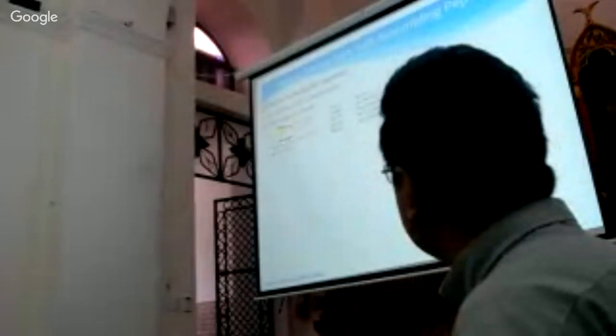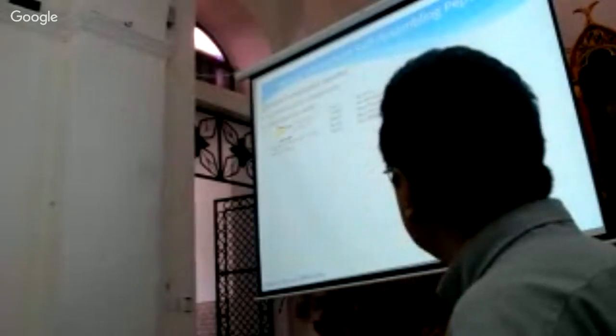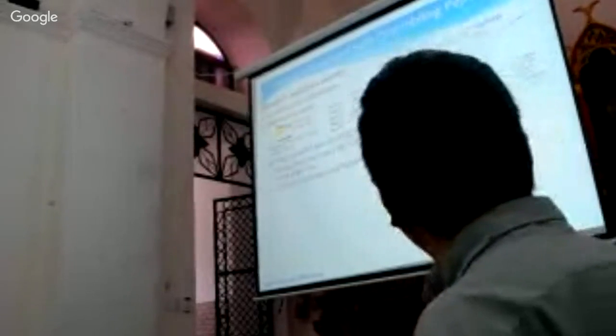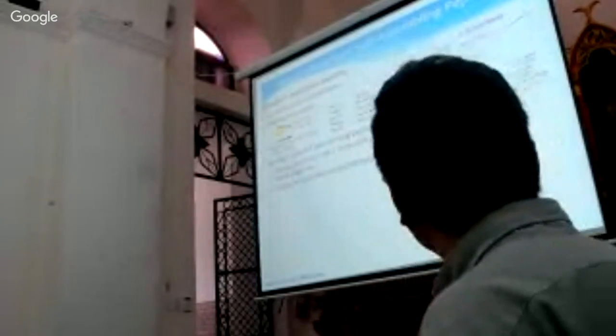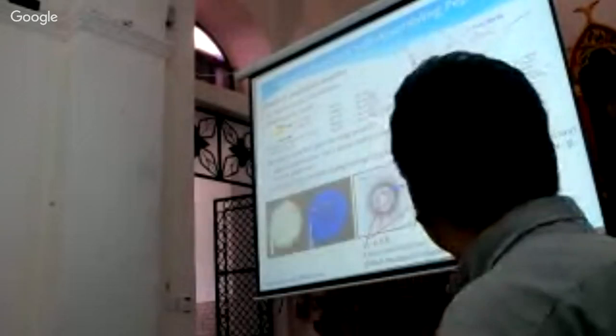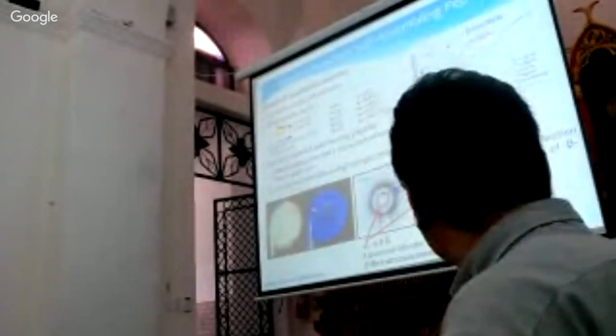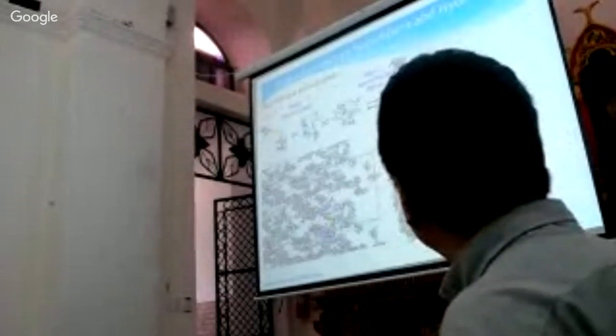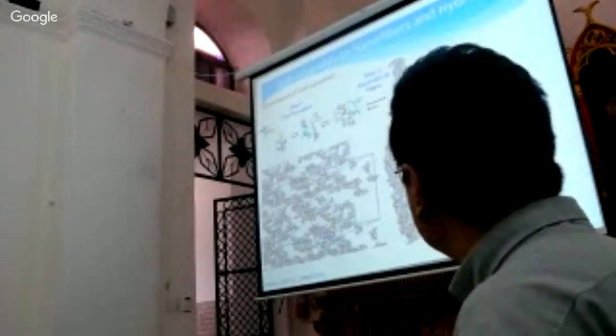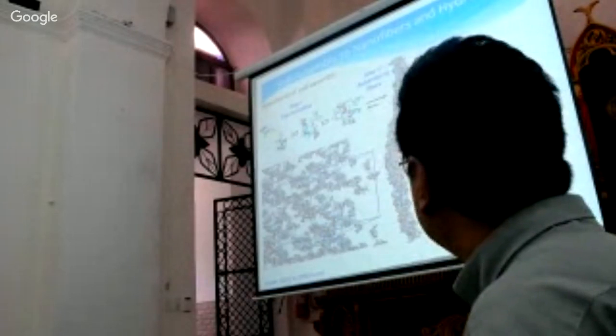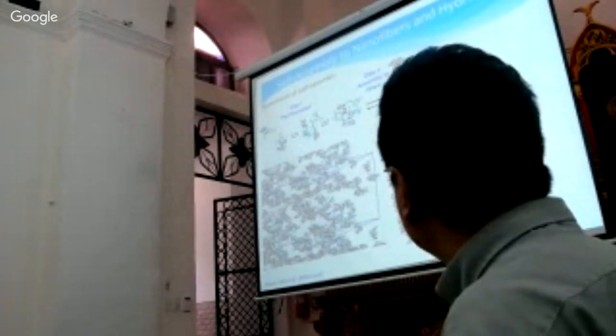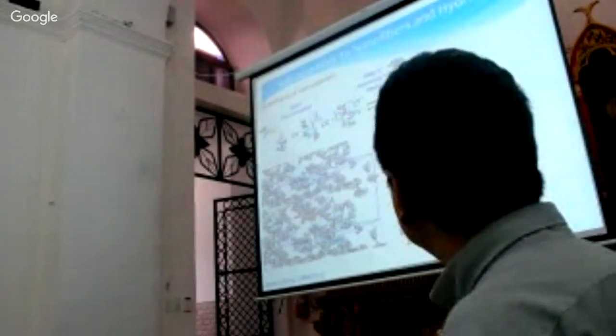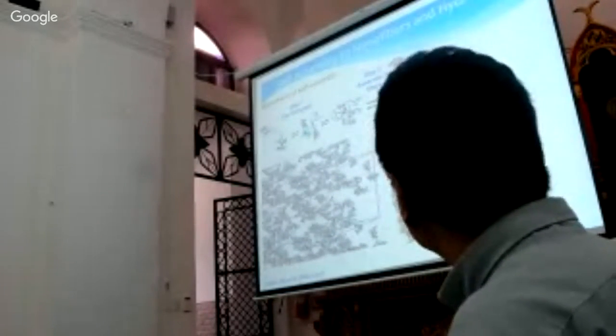The design rationale is to decrease the hydrophobicity from this end to this end, and then it will form a nice hydrogel that I'll show later. This is the secondary structure determined by the CD spectrum, and it forms beta-sheet structures, confirmed by X-ray synchrotron. And for how they are assembled in water, we collaborated with computer scientists. You see that each one represents one peptide molecule, they pack together anti-parallel and form this structure, and they form this nice fiber.